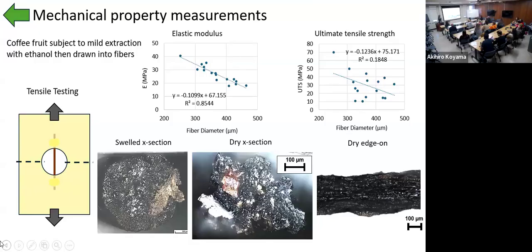But one of the issues that I found was that we could probably tap higher strength, but we're running into some geometric issues that are once again kind of an issue of spatial conservation. We're victims of the laws of physics, where we're dissolving our material. So it's upwards of 80 to 90% ionic liquid when I extrude it, and we have this nice round, smooth surface. And when you remove 80 to 90 volume% of something, you get volume collapse. And so we have these very high surface area fibers.